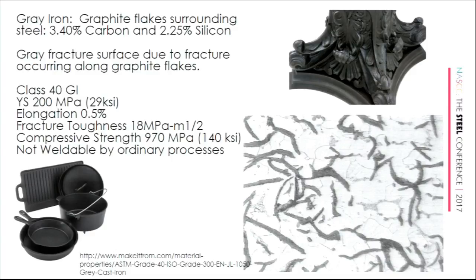And the reason it would crack, the reason it's called gray iron, is because this is the microstructure of gray iron. This is steel. If you're a metallurgist, this is pearlite, this is ferrite, that's steel. And these flakes are graphite. They're pure graphite. And while it's not clear from this cross-section, the graphite is continuous and it surrounds little puddles of steel. So when you break gray cast iron and look at the fracture surface, you're looking at the graphite, which is why the fracture doesn't look bright like steel, it looks gray like graphite. That's what makes it gray cast iron.